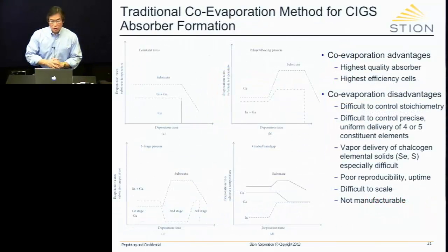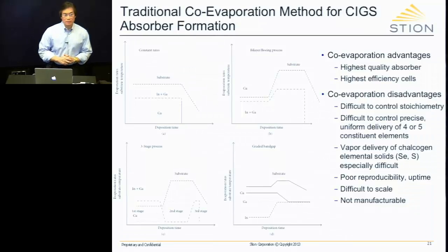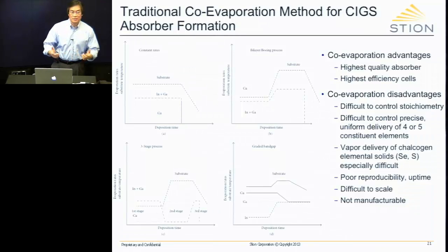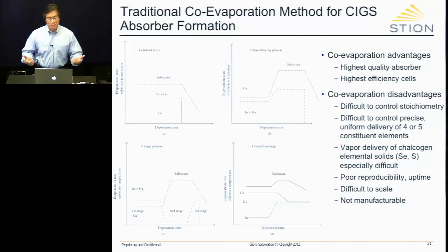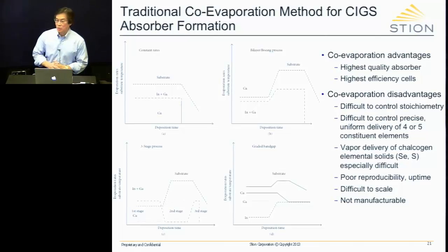So then let me go over how we make these absorbers. For CIGS, I think all of you are very familiar that one of the best absorber formation processes for CIGS is co-evaporation, no question. Right? And this is done by evaporating copper, gallium, and indium in a selenium and/or sulfur environment, whether it's H2S or H2Se. And this is done either by Knudsen cells or other things of that kind. You can do this either in 1 step, in 2 steps, or 3 steps. This just happens to be the best way to do that.